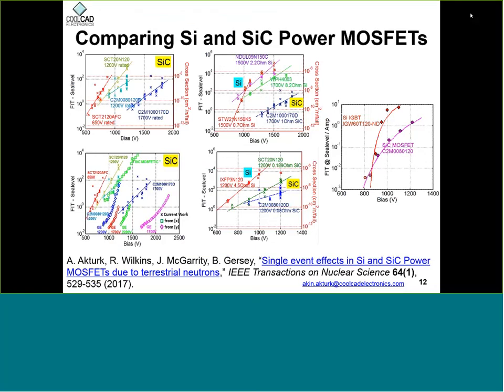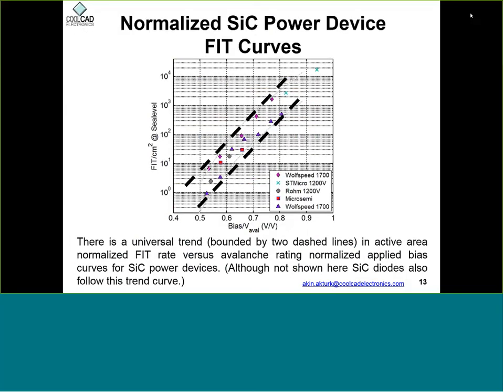So then the y-axis is scaled by area, scaled by amp, which is kind of similar to area. If you do that, then at the high voltages, silicon tends to have a higher failure rate. But at low voltages, most of the silicon devices can have a lower failure rate. So you can get a curve similar to what I'm showing here, but maybe the slope of this curve is slightly different, where you have higher failures at higher biases and lower failures at lower biases. So the curves are still similar, but the slope is slightly different.